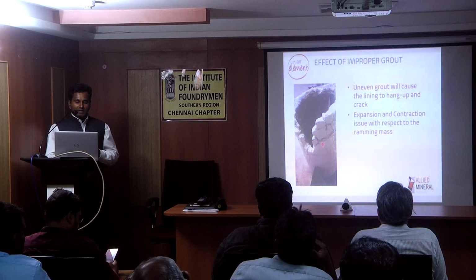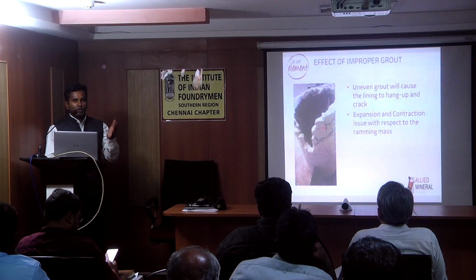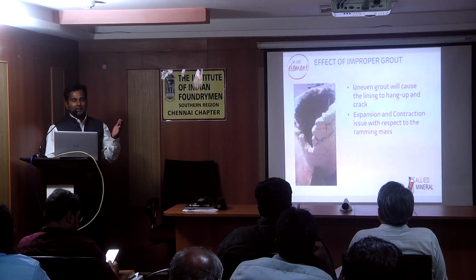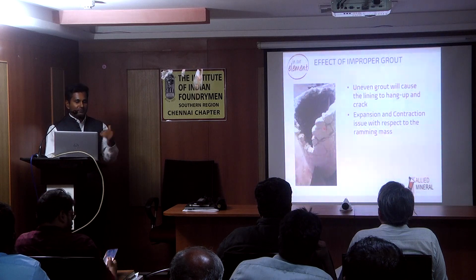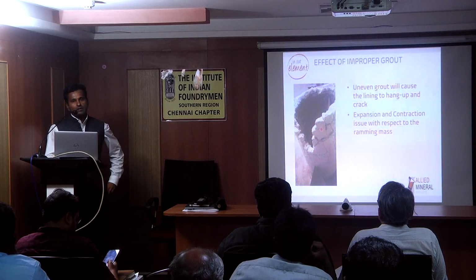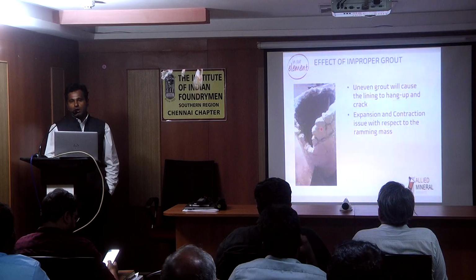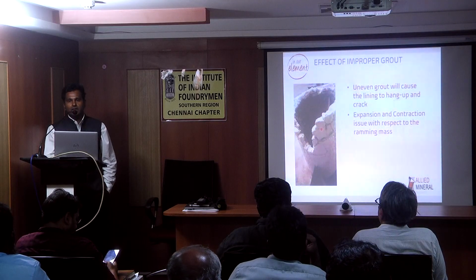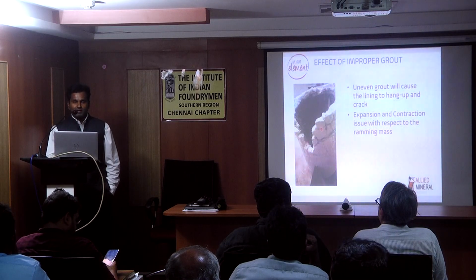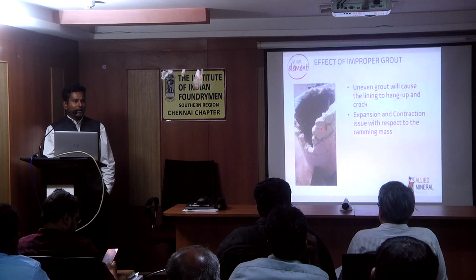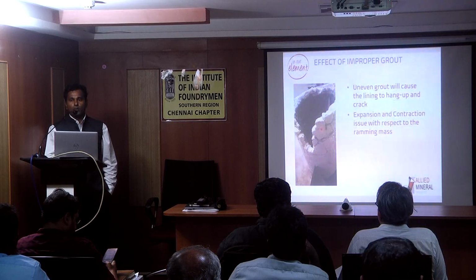Here you can see these are all the lining hang-ups when a lining tries to expand and contract. From the back, it will try to create a stress. Further, it will have a horizontal crack. A horizontal crack may not be sealed even if you do a proper cold start. Only vertical cracks can be sealed if we do a proper cold start.